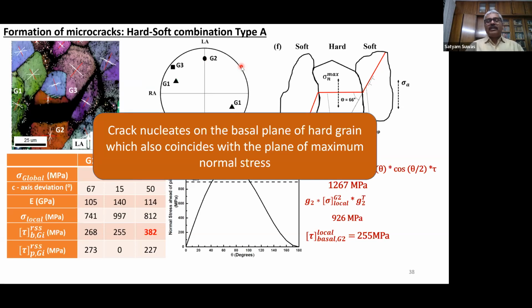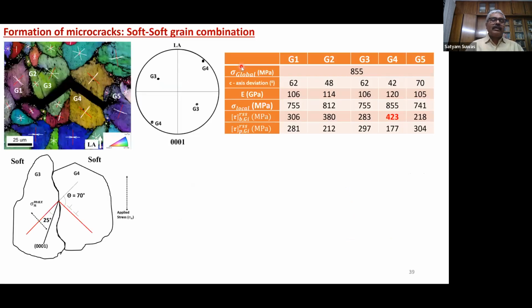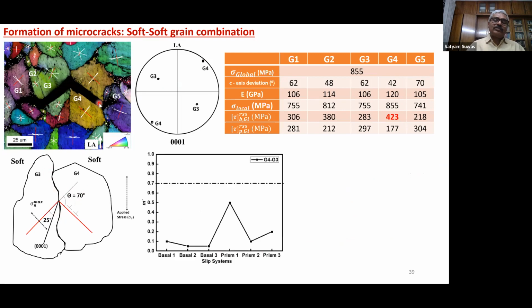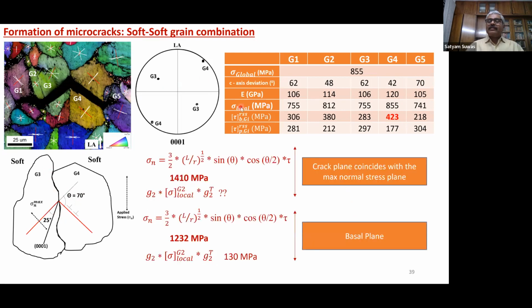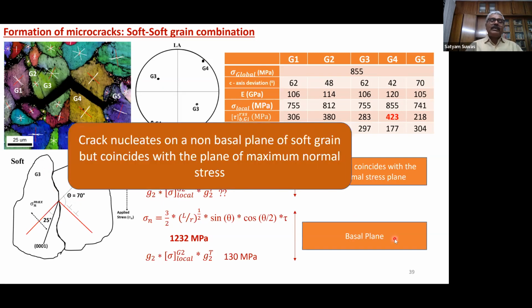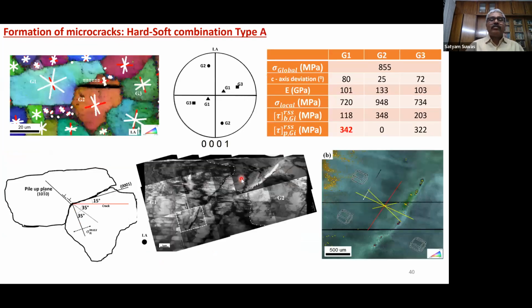Now the other combination, another crack which was examined, again G1, G2, G3 here, where we have soft grains. As I said, there were some cracks which were seen between soft grains also. In that case, the crack plane coincides with the maximum normal stress plane, and this is a non-basal plane. So here the conclusion is the crack nucleates on a non-basal plane of the soft grain, but coincides with the plane of maximum normal stress. So the second factor, orientation as well as the Schmid factor, is also playing some role. Now the hard-soft combination is also examined.